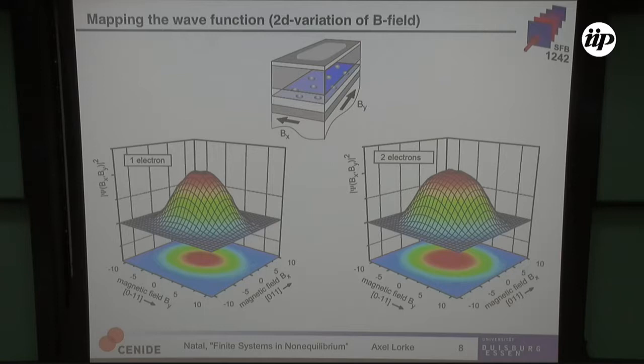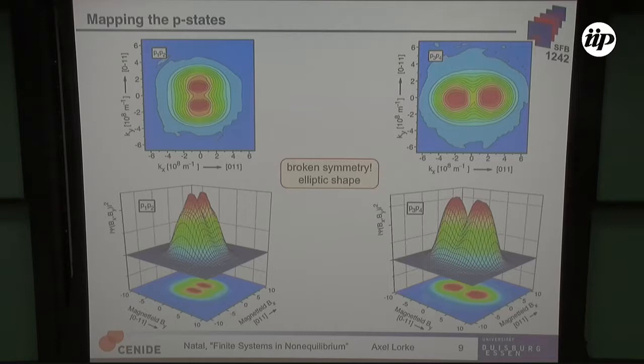A little more interesting are the P states, those you see here. For a chemist, that's quite clear. You have the PX, the PY, and in three dimensions, the PZ. But for us, this was a little bit surprising because we had thought we have a circularly symmetric quantum dot. So you would expect that anything you measure would also be circularly symmetric. But it's not. And the reason is that we are in a cubic semiconductor, and of course a cubic semiconductor will distort this, and we have some XY splitting, and that's why the lower states are oriented along one crystal direction and the higher P states are oriented in the other direction. So this was very nice because it gave us a very sensitive tool to look at the symmetry of the quantum dots.